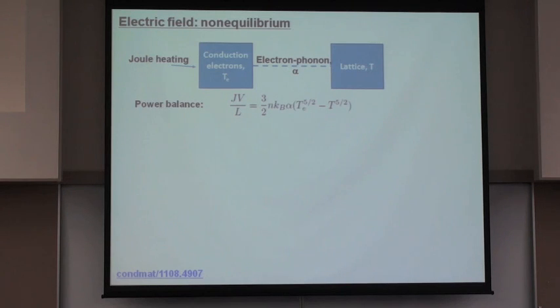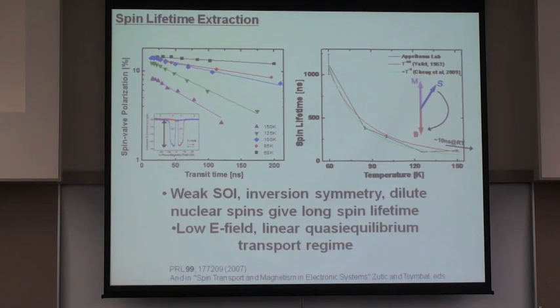Let me go back a second. Despite the fact that we can make these kinds of spin lifetime measurements by making a correlation between the spin transit time and the spin polarization, which is really nice, we haven't really learned very much more about spins in silicon than one could using electron spin resonance techniques. This kind of power law of spin lifetime has been known literally for decades simply from line width measurements of absorption and resonance.